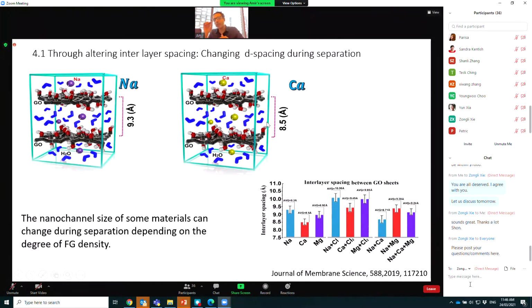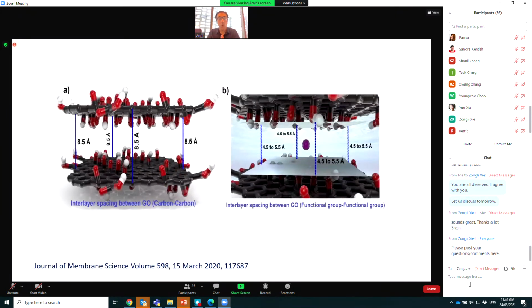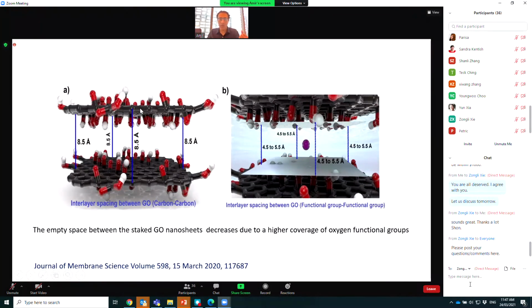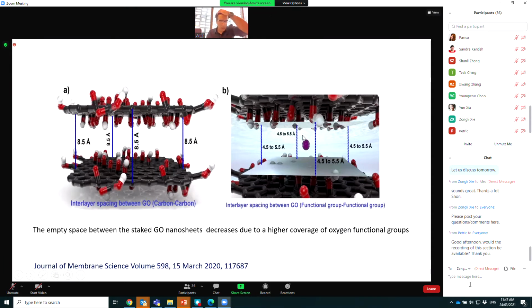So even an angstrom reduction in your nanochannel can contribute a lot to your selectivity, because we are dealing with lots of parameters inside the nanochannel. One of the things that has been ignored in the literature is the orbital overlap of the functional groups. Always, the nanochannel, the empty space for ion transfer, for 2D materials such as graphene oxide based material or other 2D nanochannels, or even other types of nanopores, is considered, for example, from carbon to carbon distance, whereas it has to be from functional group to functional group, or from orbital to orbital.